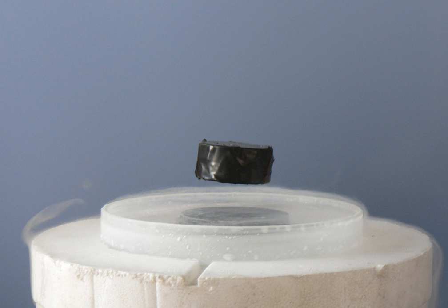Although niobium-titanium boasts less impressive superconducting properties than those of niobium-tin, niobium-titanium has, nevertheless, become the most widely used supermagnet material, in large measure a consequence of its very high ductility and ease of fabrication. However, both niobium-tin and niobium-titanium find wide application in MRI medical imagers, bending and focusing magnets for enormous high-energy particle accelerators, and a host of other applications.